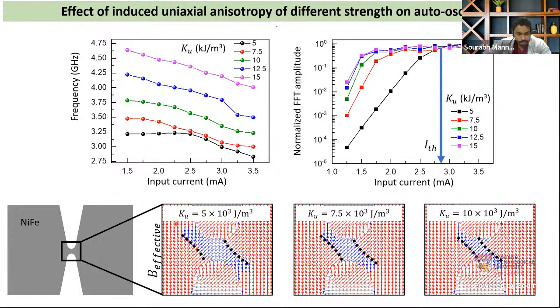So we see that in the effective field region near the nanoconstriction region, there is a confinement, as is shown by these blue arrows. So we see that there is a change in the effective field behavior, and because of that, there is a confinement of the auto oscillation near the constriction edges. And as we increase this Ku value, the anisotropy value, this confinement region shrinks down. And what is the consequence?